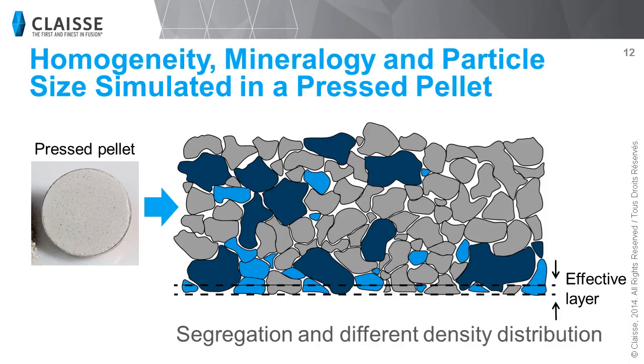Now, if we look closely at the press pellet surface, that's what we see, roughness and inhomogeneity of the specimen. The grinding of different mineralogical phases and composition produces particles that have different size and shapes and which will react differently when the pressure is applied to produce the pellet. This most probably leads to segregation of different materials of the sample with different density distribution. This will affect the penetration depth of the X-ray for a given wavelength of interest. This illustration shows that the effective layer is not homogeneous and not representative of the overall sample composition.